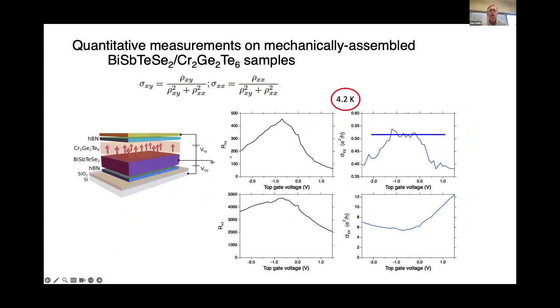So the magnitude of the Hall resistance as a function of top gate voltage is on the left here, and the longitudinal resistance on the bottom left, both peaked near the Dirac point. If we take those data and translate them into Hall conductivity and longitudinal conductivity, this is what we see. So longitudinal conductivity takes the value very close to 1/2 e squared over h over a range of top gate voltage. It's not precisely quantized to part per million values. It's ranging between 0.48 and 0.52 in different devices.